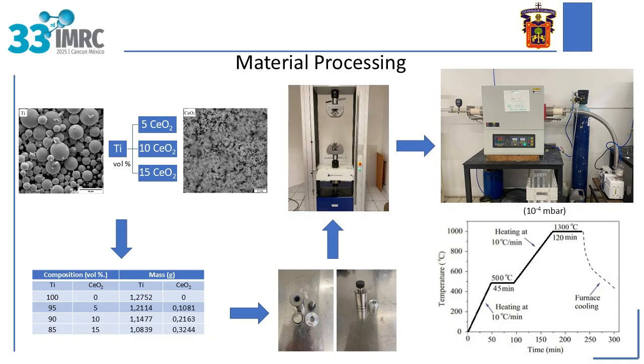The sintering process was carried out following isothermal ramps. First, the samples were heated at a rate of 10 degrees Celsius per minute, up to 500 degrees for 45 minutes. Then the samples were heated to 1300 degrees Celsius, where they were maintained for 120 minutes. Finally, the furnace was cooled slowly to extract the samples.